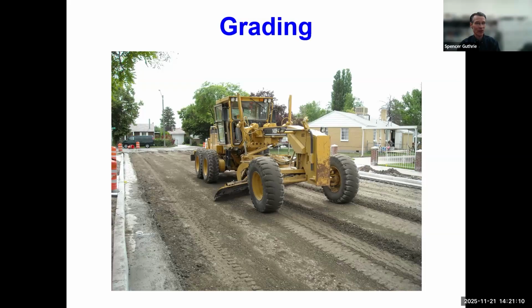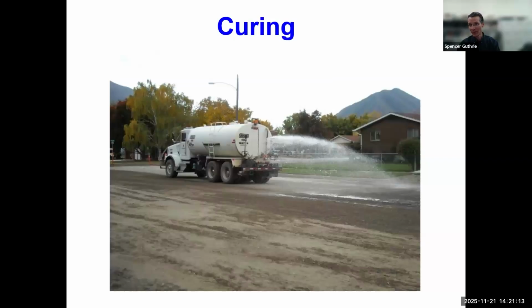Okay, after the grading is finished, it's time to cure it. Just like we cure concrete, we cure a cement-treated base. Our intent isn't so much to add water to the layer, it's to prevent the water that's already there from evaporating. That's the same concept that we use for concrete. When we put concrete cylinders that we've cast in the laboratory into a fog room, we're just surrounding the cylinders with 100% humidity to prevent evaporation. Well, here, out exposed to the wind and the hot air, evaporation is constantly happening.